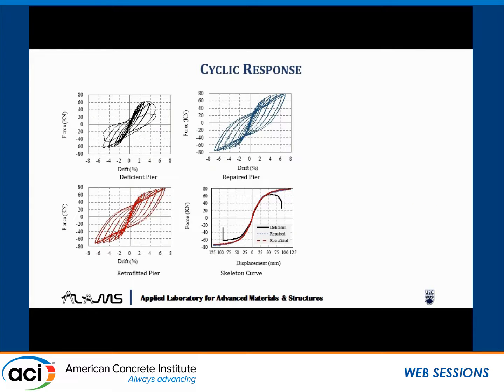So this is the deficient pier. We tested it, and we could test it beyond 4%, and after that, you had significant buckling of rebar, and then it could not take any further load. So it's a significant reduction in the stiffness as well as load. And then this is the repaired pier with GFRP. It shows a very stable hysteresis loop, and you see that the capacity kept increasing. We actually could not go beyond this because it is going beyond the stroke length of the actuator.